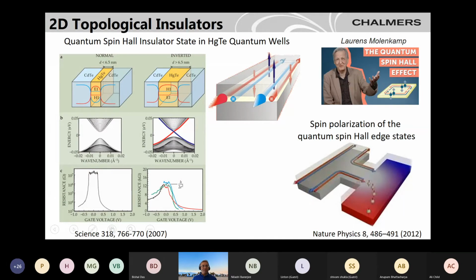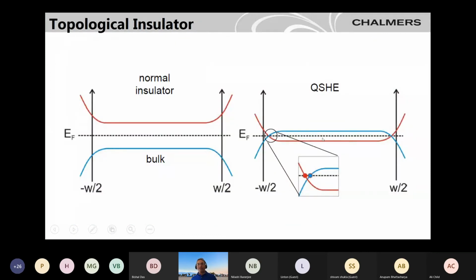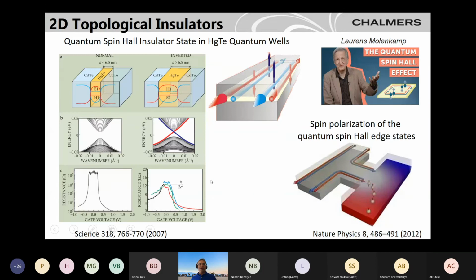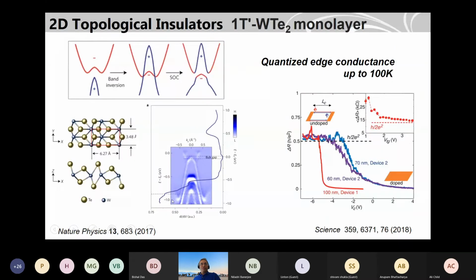But you see, it's not very well quantized. There is a lot of noise in the measurement, and that is coming from the band gap you open. So let me go back one slide. The inverted gap you open is very low, around 10 millielectron volt. You have to do very low temperature measurements because you have to stay in the gap of this band inversion. And also because of impurities and things like that, you don't get very good quantization. In the quantum Hall effect the quantization is really flat, up to 9 or 10 decimals, but here it's not the case.